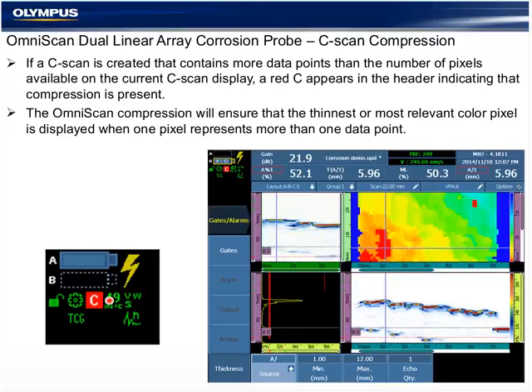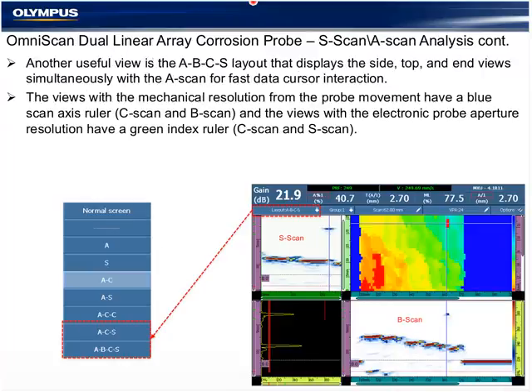In a compression mode, it means that 1 pixel on the display can represent 4 or 16 data points in the file. And the compression mode ensures that the most significant data point, which in corrosion would be the thinnest, is always represented by the color. As I zoom in or change displays to a larger C-scan, eventually that C goes away. This is blind to the user and only a visual indicator. It requires no configuration. It's just a visual indicator to be aware of the compression of the C-scan.